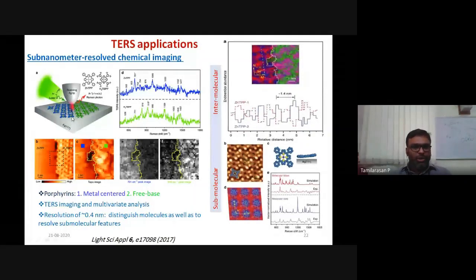So they have coated a thin film of both of these, like a metallic center and free base center, and they also form a very clear interface between these two. You see this one. These two porphyrins have their own corresponding Raman spectrum. Just the blue one is the metallic center, and the green one is the free base center. So they have mapped the interface with AFM. You can clearly see the interface, and it is the magnified region.